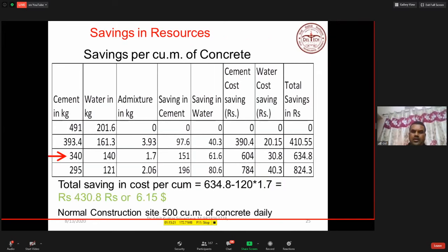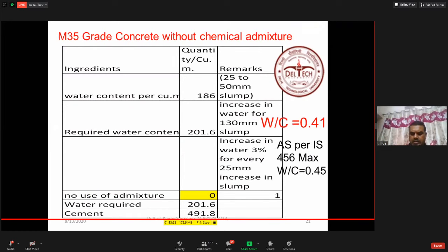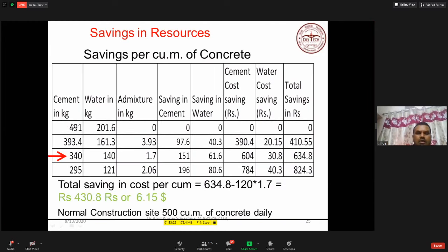Now similarly, if I keep on calculating, what we will see if I use chemical admixtures which can reduce the water requirement, like 20%. So 201.6 minus 20% of 201.6, if I do, I will get the water reduction. And once I get the water reduction and water cement ratio, I can again calculate the cement reduced. So now I want to present this in the form of this. You see, if I am not using any chemical admixtures, water required is 201.6 kg, cement required is 491 kg, so there is no saving. Now suppose I have used an admixture which is reducing the water by 20%. Then water required is 161.3 kg. For the same water cement ratio, I will be requiring 393 kg of cement, and then admixture required like something like this. So this is the calculation. We got the cement and water saving.